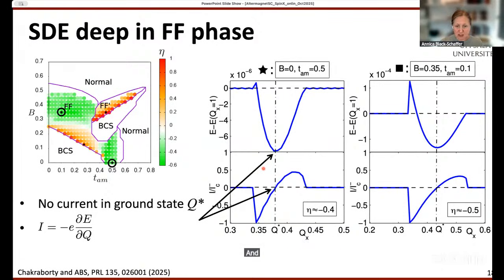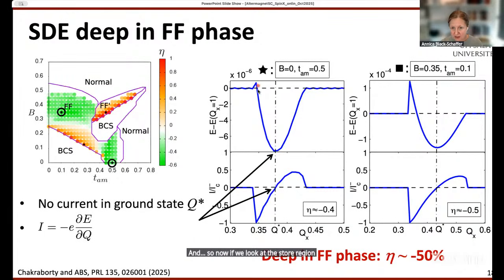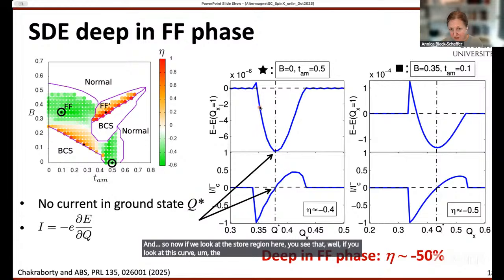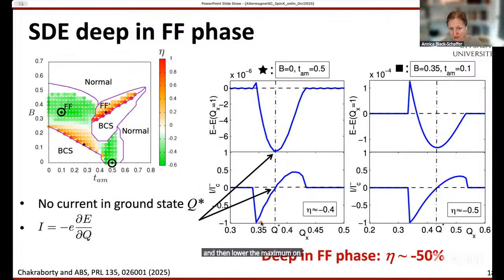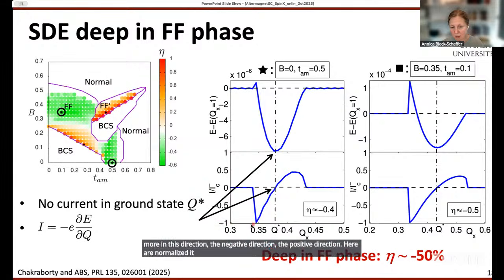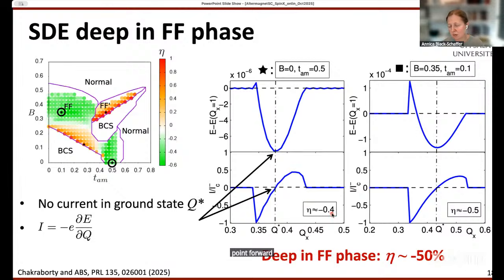So now if you look at the star region here, if you look at this curve, the derivative is higher on this side and lower, at the maximum, on this side. That means the current is going to be more in this direction, the negative direction. Here I normalized it, so it reaches -1 at most, and it goes up to about 0.4, so efficiency -0.4. And very similar in this square region here.